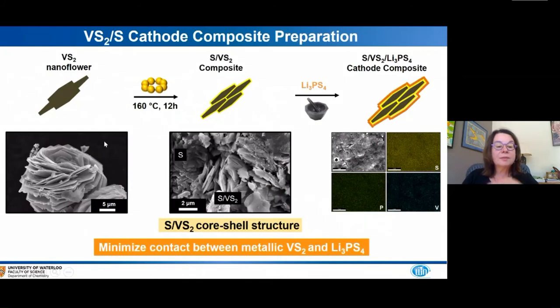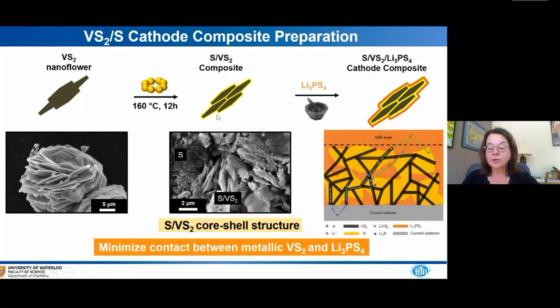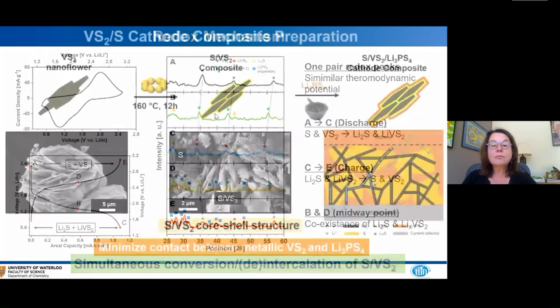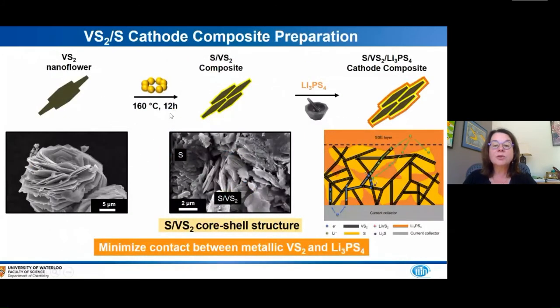We call these nanoflowers, they have basal dimensions on the order of 10 microns and are very thin layers of VS2. These can be easily mixed with sulfur using a traditional melt technique at 160 degrees for 12 hours to produce these composites.